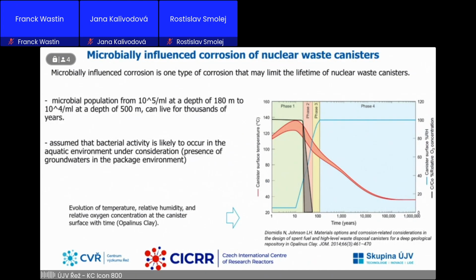Microbial influenced corrosion is one type of corrosion that may limit the lifetime of the nuclear waste canister. Also, the risk of microbial corrosion is low. The definite proof is missing. In the figure, you can see a model evolution of temperature, relative humidity, and relative oxygen concentration at the canister surface with time. Based on this model, we can expect microbial corrosion at phase 4 under anaerobic conditions during saturation of bentonite.